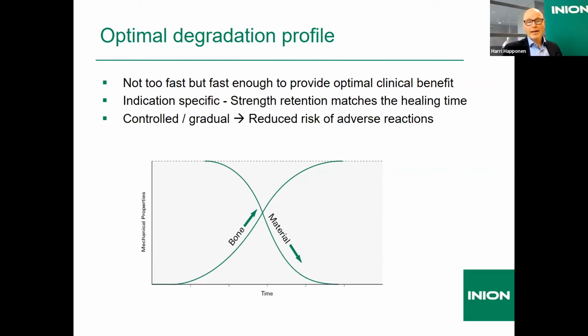However, then in the spinal indications, you need to have a longer strength retention time, and you need to select a different kind of polymer for those applications. So that's what we are doing at Inion. And with the Inion, we can always as well guarantee that the degradation of the implant is controlled and gradual, minimizing the risk of adverse reactions.